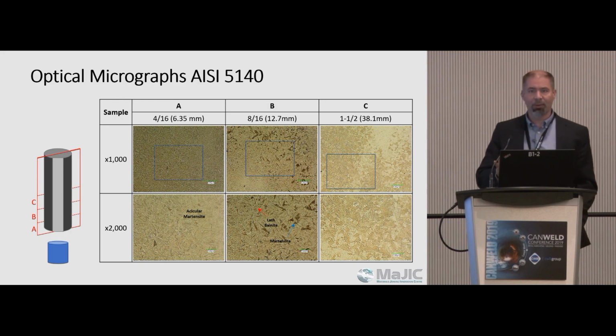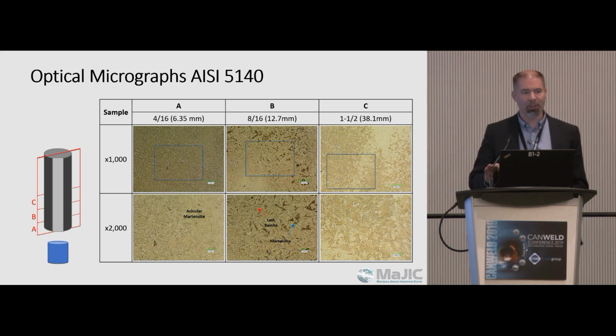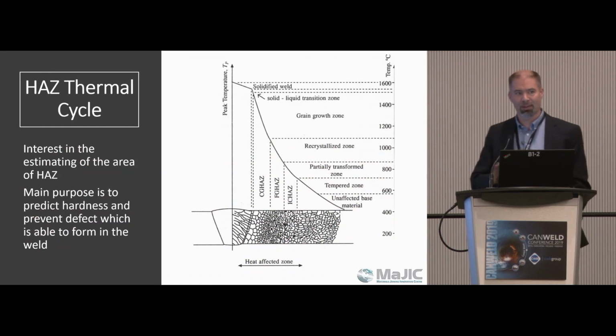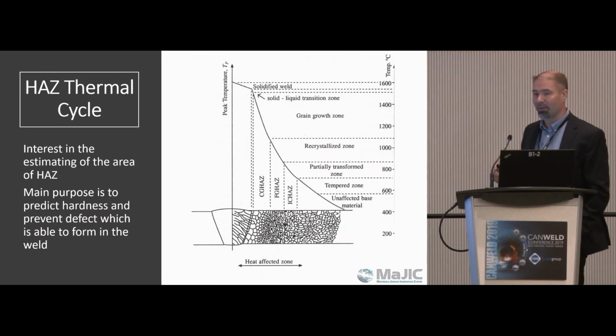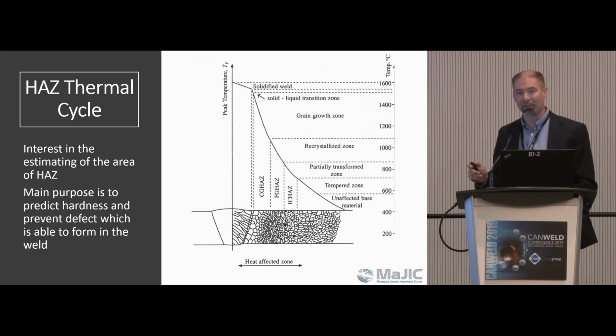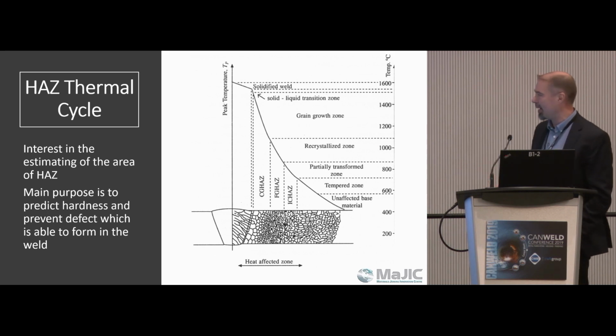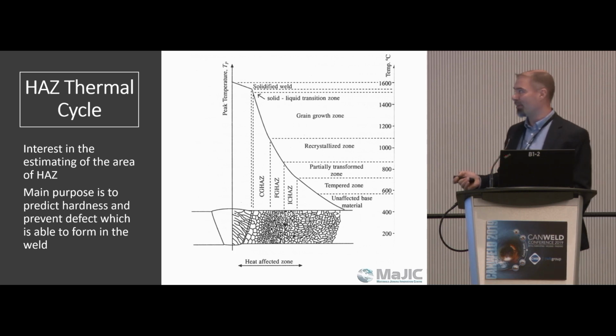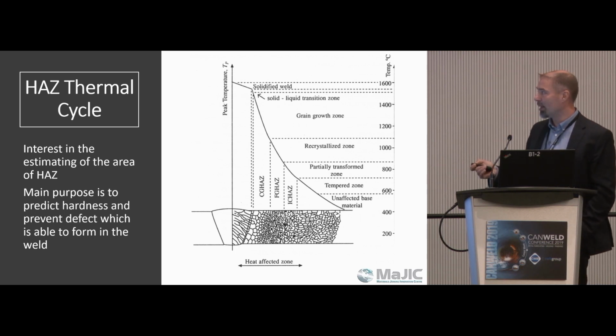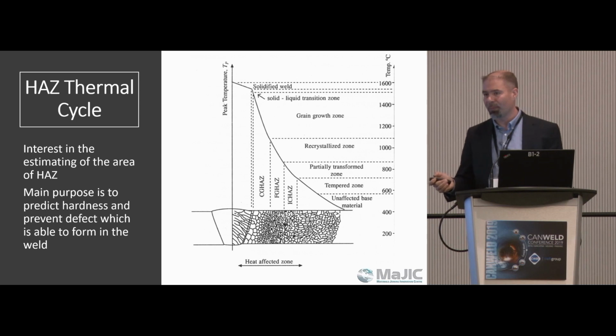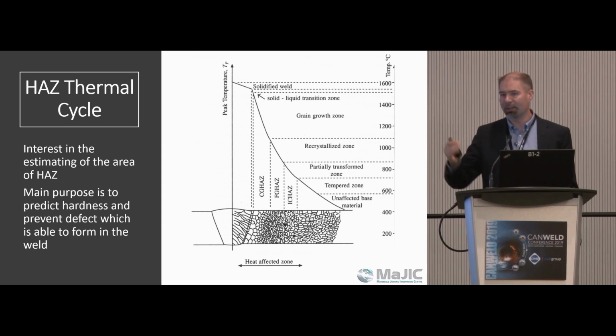Just a little note about the heat-affected zone thermal cycle. I think this particular figure has been thrown up on the screen several times in the last day and a half, so most of you would be very familiar with the thermal cycle in the heat-affected zone. But what we're looking at is this coarse-grained heat-affected zone primarily, where we end up getting up over the austenitizing temperature and then cooling down very rapidly.